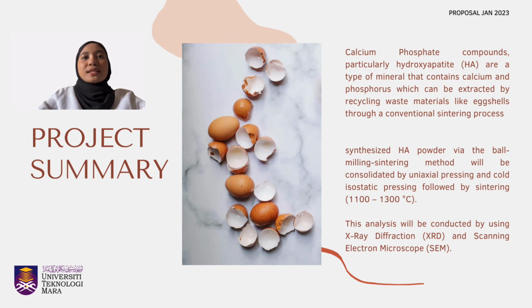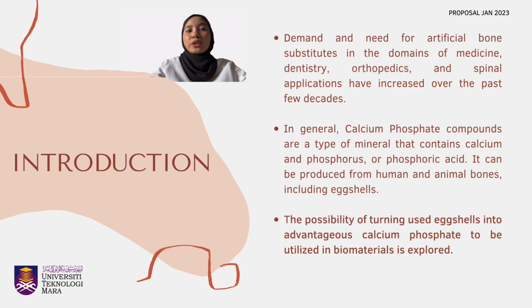In this work, synthesized HA powder via the ball milling sintering method will be consolidated by uniaxial pressing and cold isostatic pressing, followed by sintering at 1100 to 1300 degrees Celsius. The sinterability of the powder will be evaluated in terms of its phase transformation and morphological evolution, and subsequently compared to the commercial HA powder. This analysis will be conducted using X-ray diffraction and scanning electron microscope. Now, let's move to the introduction.